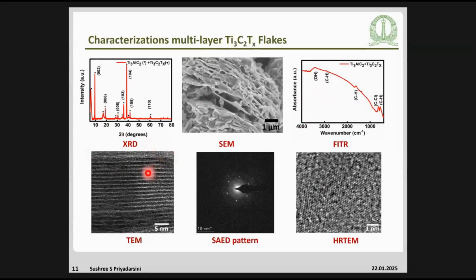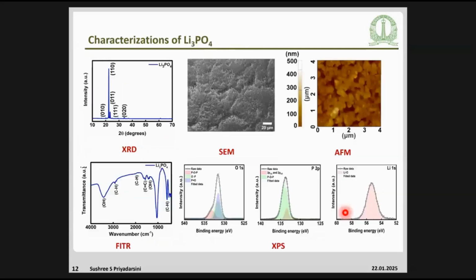When you see that under TEM, you see this layer structure. To understand also the crystal structure, we have done SAED and also HRTEM, where you see the crystals present there in hexagonal crystal symmetry. Now let's move to the characterization of lithium phosphate. You can see that in the 110 direction, it's a preferential growth.